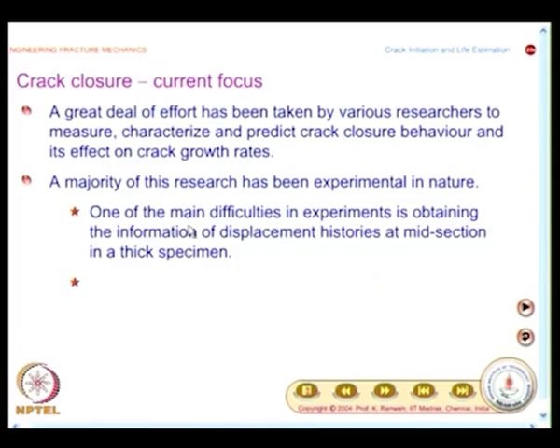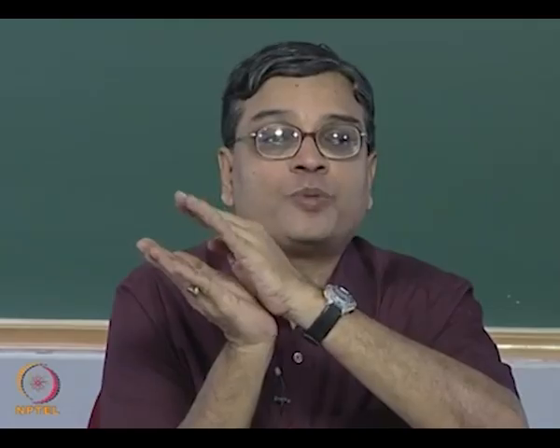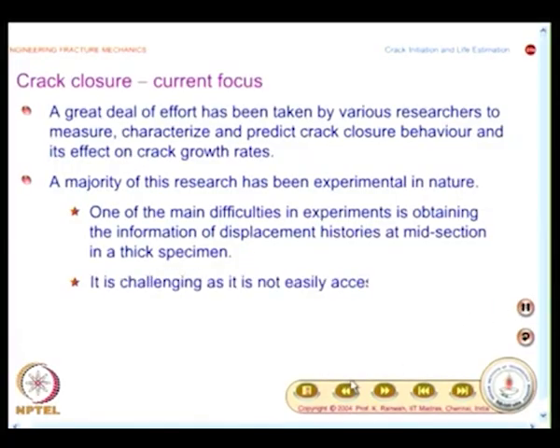And what is the main difficulty in the experiment? One of the main difficulties in experiments is obtaining the information of displacement histories at mid section in a thick specimen. See, I have already mentioned the crack opening is not uniform along the front. So, you have to ensure if I have a thick specimen, the in between portion whether it has opened or not, I have to have experimental measurement, only then it will be more realistic. That poses a challenge. It is challenging as it is not easily accessible.